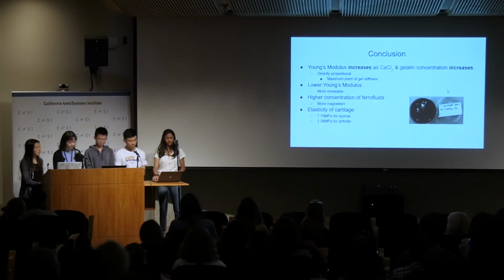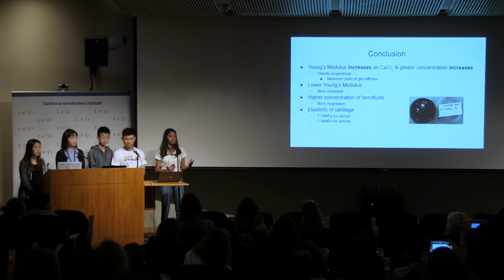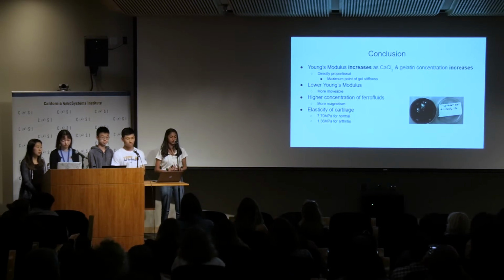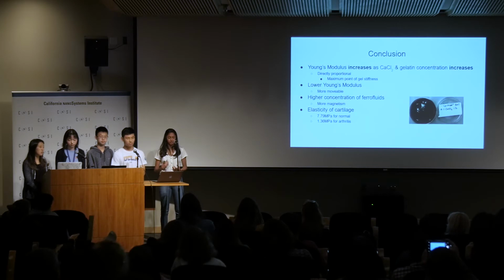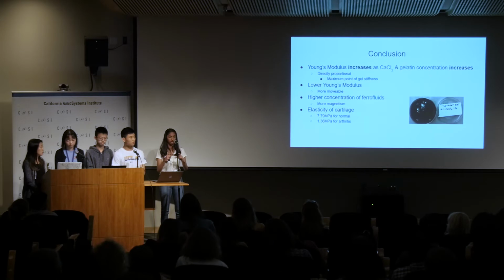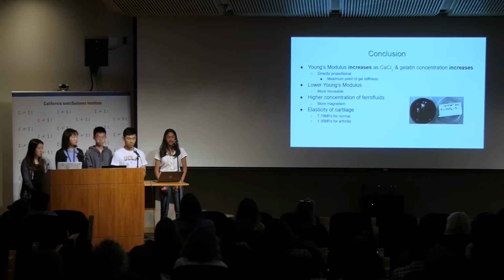So in conclusion, as we saw through the graphs, the Young's modulus increases as the CaCl2 concentration increases as well, and gelatin, as we added more of the concentration of the actual biopolymer, it added more of the liquid and solid substance that we were looking for and hoping to receive. And it was directly proportional, so as both of them increased, it both increased at the same time. And this is until it reaches the maximum point of gel stiffness before it reverses the reaction and becomes a liquid once again.